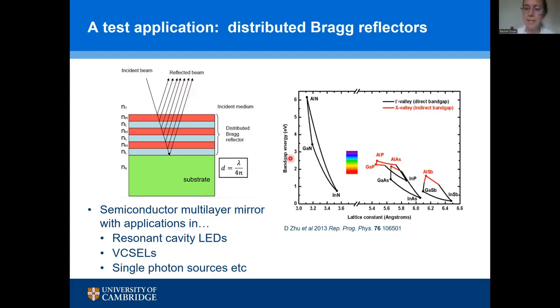Now, back in this diagram I had when I was talking about the band gap, we can talk about now, using this diagram, how we might create a distributed Bragg reflector just using pairs of semiconductors without any porosity involved at all. So if I was in the arsenide material system, I would use gallium arsenide and aluminium arsenide. They have roughly the same lattice constant. You can grow beautiful multi-layers just like this with very, very high reflectivities by growing an awful lot of layers.